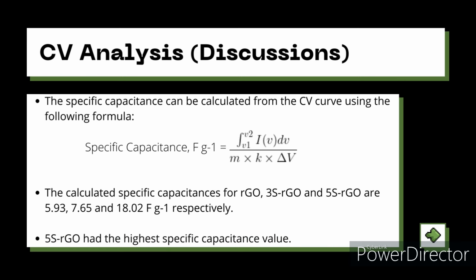From the CV curve, we can also calculate the specific capacitance using the following formula. The calculated specific capacitance for RGO, 3S-RGO, and 5S-RGO is 5.93, 7.65, and 18.02 farads per gram respectively. Again, 5S-RGO had the highest specific capacitance value.